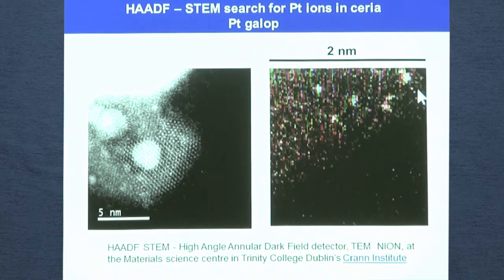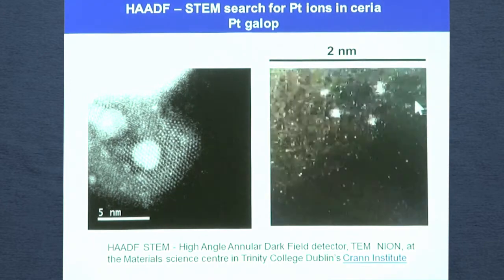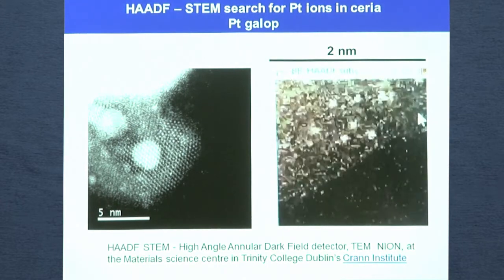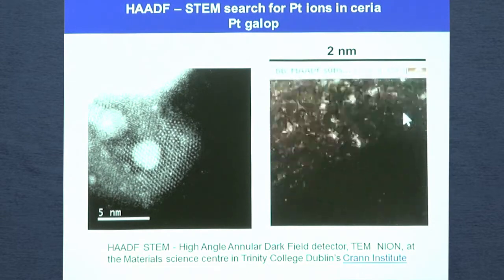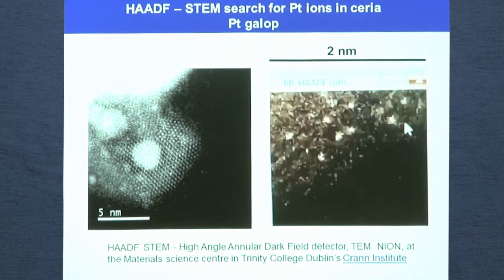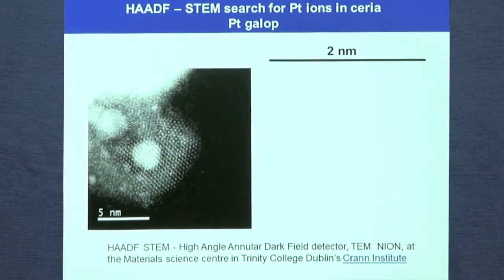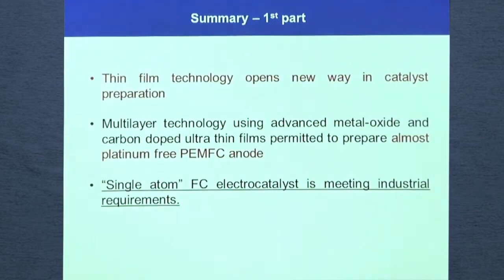this single atoms. This is what we call the platinum galop, because they are the single atoms of platinum which are moving because they are excited by the electron beam. Unfortunately, we cannot obtain a stable image because the energy was 200 kiloelectronvolt, and the platinum just makes hops in between these specific positions where the platinum ions are stable. But at least this is some proof of atomically dispersed platinum.